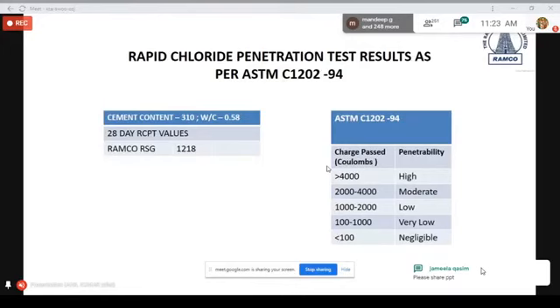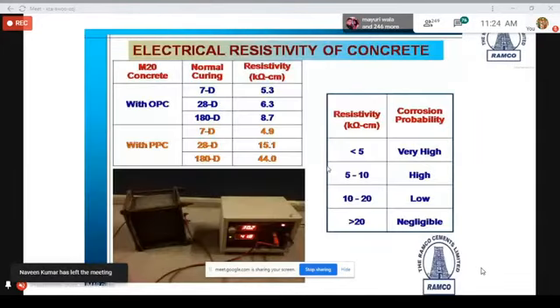This is another test which we call the electrical resistivity of concrete, which is based on the resistivity in kilo ohms centimeter. If the resistivity is lower, that means the probability of corrosion is very high. So the resistivity value should be much higher so that your corrosion probability is lower. So you can see the values: M20 concrete with OPC, 7-day, 28-day, 180 days of test, you will find that the resistivity is much lower. That means the probability of corrosion is much higher. Whereas with PPC, you will find that at 180 days or 28 days for that matter, the resistivity is much higher.